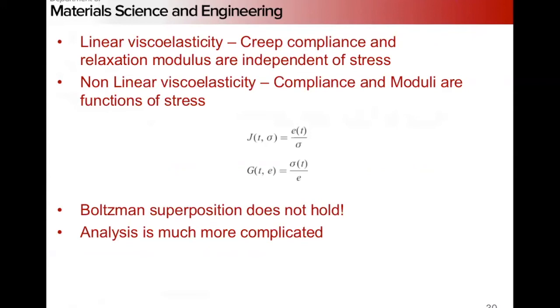Nonlinear viscoelasticity, right? In linear viscoelasticity, the compliance, creep compliance and relaxation modulus are independent of the stress. So if we move into a nonlinear viscoelastic regime, the compliance and moduli are explicit functions of stress. The Boltzmann superposition doesn't hold. You can't just simply add up everything in the same way. The analysis gets much, much more complicated, right? And so the point of going through this is not so much for you to work through everything and try and do the analysis, but just to appreciate that the reason why we assume everything is linearly viscoelastic is because the nonlinear analysis just gets nasty very quickly, and you have to resort to simulation.